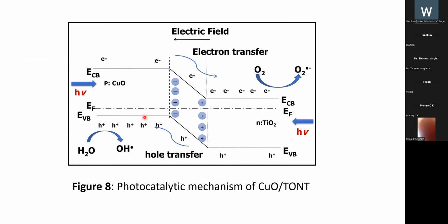The photocatalytic mechanism is shown in figure 8. CuO/TONT responds to light radiation, producing electron-hole pairs. The photo-generated electrons and holes move in opposite directions at the junction and enable effective separation of the electron-hole pairs. The potential barrier at the junction helps in building a space-charge separation for a longer time.